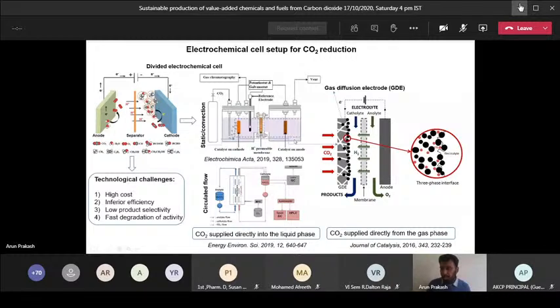Like for potassium bicarbonate, here you can see for potassium bicarbonate, 0.5 molar bicarbonate and 1.5, it will drop from pH 8 to 7 or 6. So depending on the pH, you have to consider the pH after saturating your solution with the CO2.